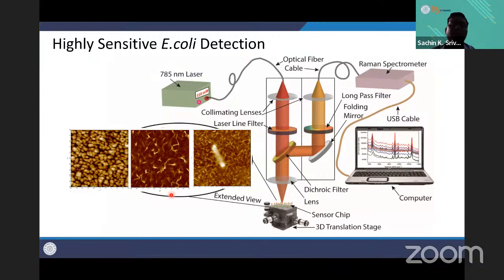We have used it for detection of E. coli bacteria. So what we are doing here is that you have this film, and we attach T4 bacteriophage viruses, which bind very specifically to E. coli bacteria. You can see that E. coli bacteria are here. Light from the laser comes like this, and I have a filter here so that clean laser light comes like this, and then the light which is getting scattered from here is sent this side. Then I put a long pass filter so that it cuts the laser light, and only the Raman signal goes to the spectrometer.